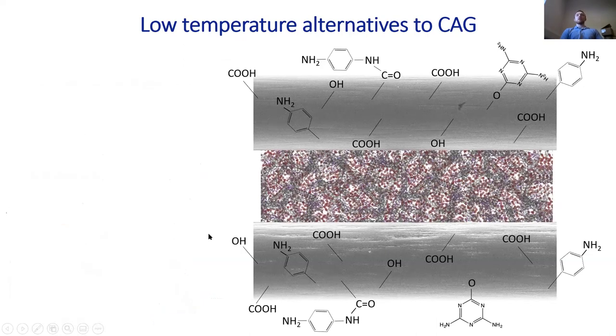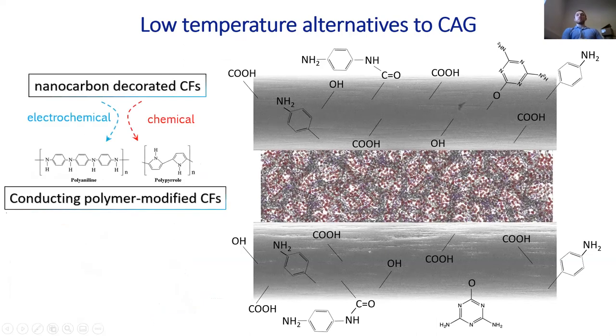The last step would be deposition of pseudocapacitive materials inside of the nanocarbon pores as well as the carbon fiber surface. For this purpose, in our low temperature route, the ideal material would be conducting polymers, because they don't only give contribution to pseudocapacitive electrochemical properties, but also can contribute and give rise to mechanical stability of our electrodes.